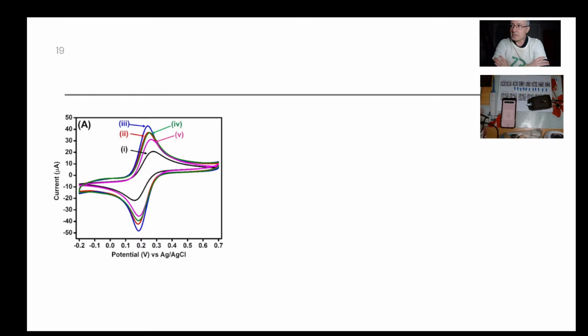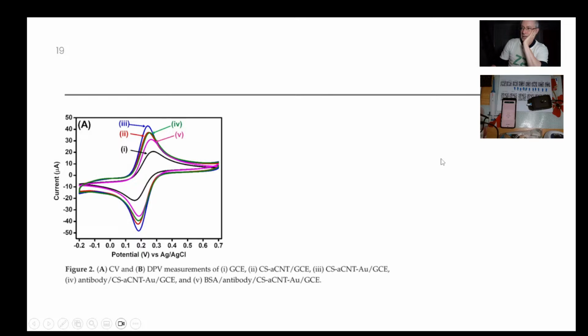Again, you're able to follow this kind of functionalization. This material is out of their paper, so I just want you to know that, and I'm only reviewing it in order to think about how to translate it. When you read a paper like this, what you find out is when you put the carbon nanotubes down, they're doing functional steps and then checking it with ferrocyanide. So they've got their pristine glassy carbon electrode, and then when they functionalize it with their carbon nanotubes, the sensitivity goes up a little bit, and they're basically just adding extra roughness to the surface with these carbon nanotubes, or extra surface area.